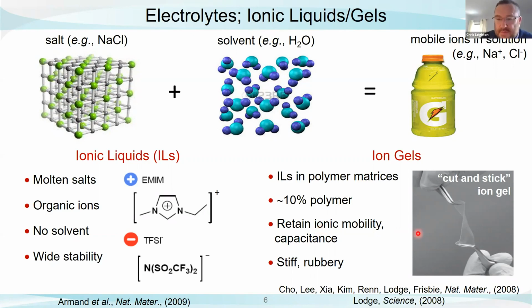In fact, the way we use this is we spin cast it on a sacrificial wafer. It's something like 50 microns thick. We can then cut it with a blade. We can literally pick the material up with tweezers. It's rubbery. And then we can laminate it in what we call a cut and stick process on the surface of any material that we're interested in building a transistor from. So it's a very, very simple, elegant way to build an electrolyte gate transistor.